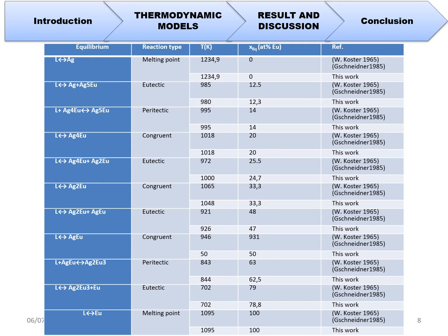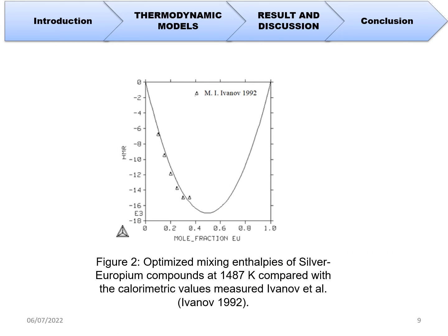We can also show the comparison between the enthalpy of mixing of liquid in silver-europium concentration measured experimentally by Ivanov et al. using isoperibolic calorimetry, and those calculated in this work. We can also show the great accordance with this experiment.